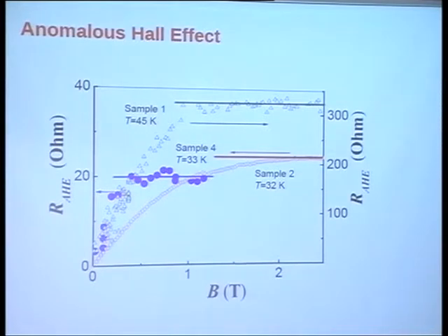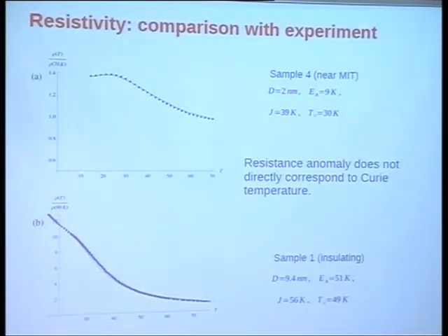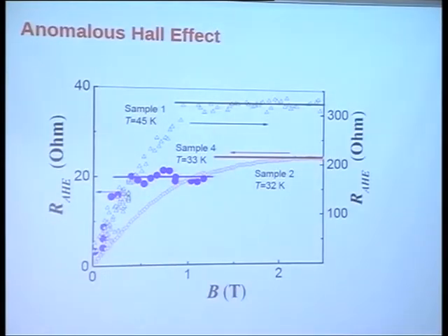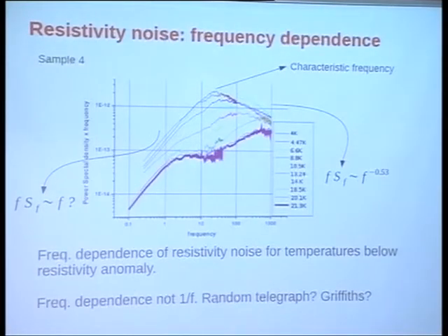Okay, so notice that this mismatch between the position of the resistivity anomaly and the Curie temperature had also been anticipated in the anomalous Hall measurements which I showed you earlier, which means the thing goes substantially ferromagnetic at relatively high temperatures. The anomalies don't capture it right then, for the reasons described.